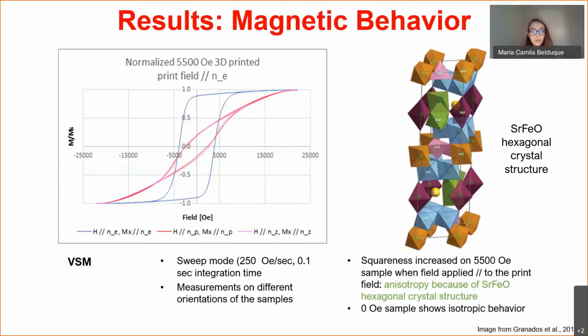5,500 Oersted sample. On the vertical axis, we can see M_R over M_S, which refers to the squareness ratio of the material. A well-defined square means that the domains controlling the direction of magnetization are well-oriented in the same direction and are hard to move. This anisotropic effect is common in ferrites because of the hexagonal structure, and indicates a high coercivity in the material, which means that it is hard to demagnetize by either high temperatures or high magnetic fields.